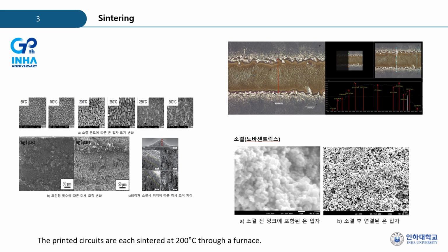The printed circuit was sintered in an electric furnace at 200 Celsius for 10 minutes, 1 hour, and 2 hours respectively. The left is the experimental result of Fraunhofer Institute. Upper right is a picture measuring the shape and lines of the sintered line. In picture A, you can see the particles before sintering, and in B, you can see the sintered particles. The picture on the right shows that our experimental result has a particle size similar to that of the picture on the left.